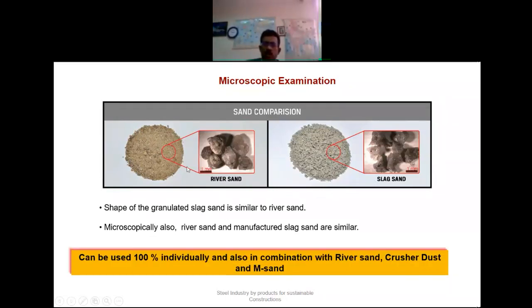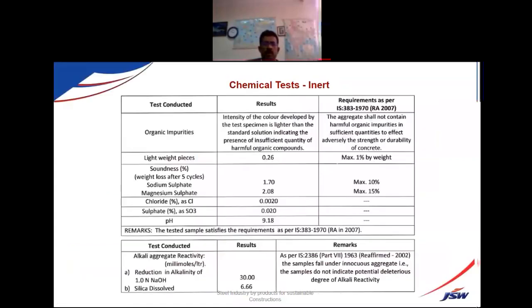And also, through various research work, we have found that even though the code is now giving about 50% replacement for plain concrete and 25% replacement for structural RCC, we can use 100%. We have done various studies, and we are now requesting the Bureau of Indian Standards to allow us to go with 100% replacement. That may happen very soon.